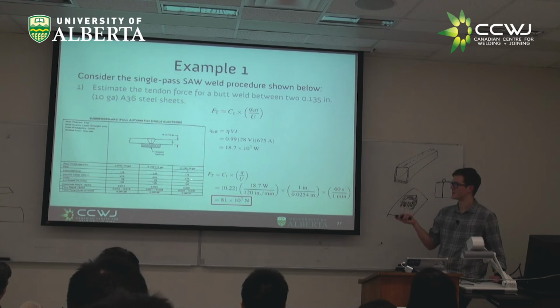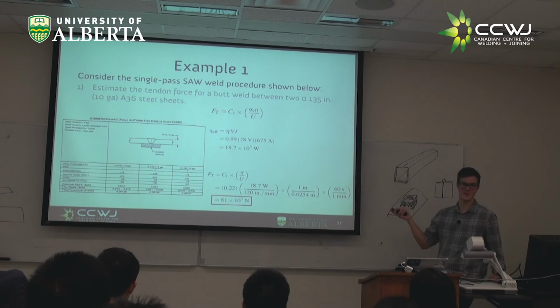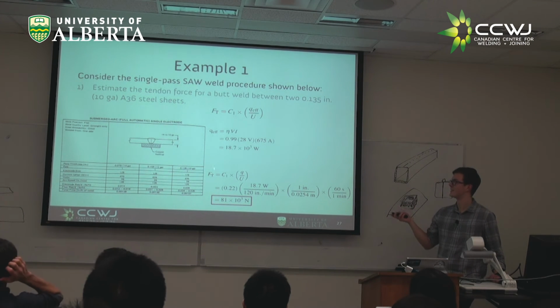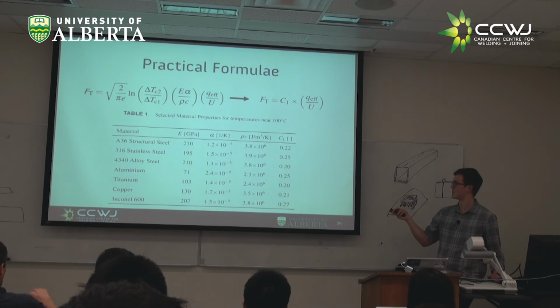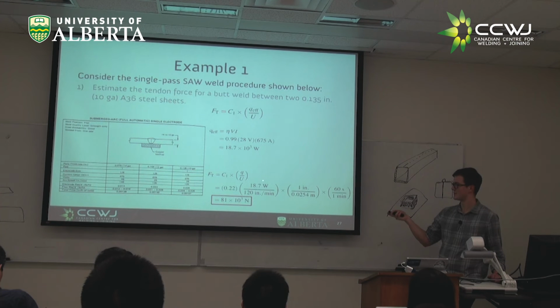Now if we look at the voltage, 28 volts, the current, 675 amps, we can calculate our effective heat input, 18.7 thousand watts. Tendon force is as simple as plugging in that value and multiplying by our coefficient. Now we said it was A36. We go back, A36 structural steel, 0.22. 0.22 times 18.7 thousand watts. Divide by our travel speed here. Our travel speed in procedure handbook is given in inches per minute, so we convert inches to meters, minutes to seconds.